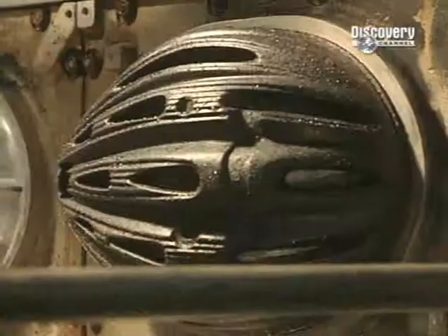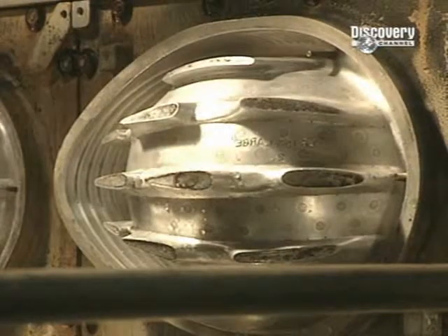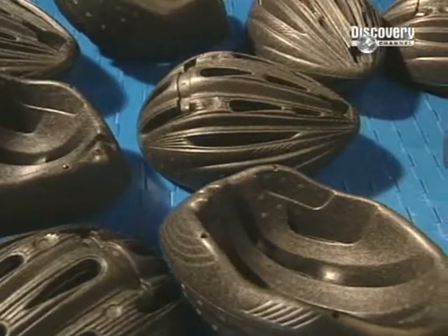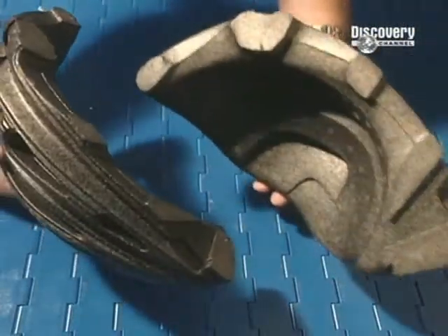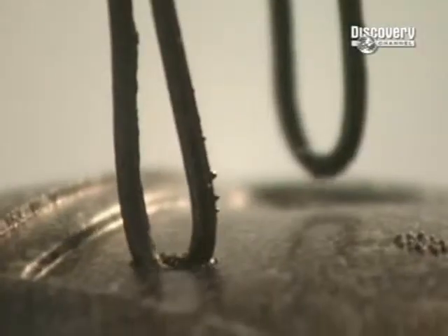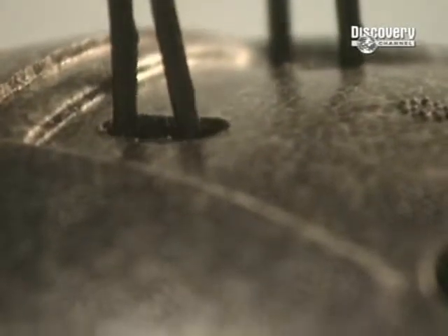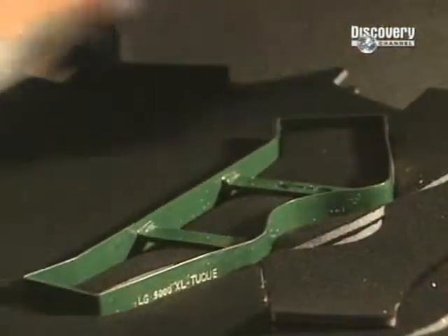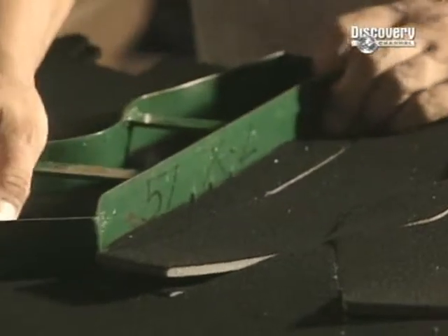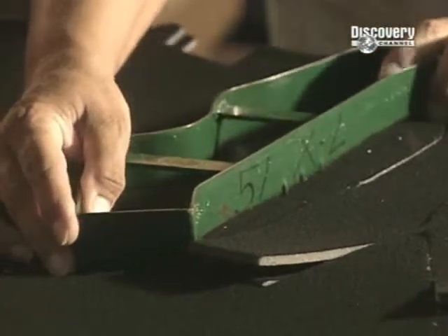The press closes up for 6 minutes. The particles are steam fused before being cooled with water. The foam is removed from the mould. Different designs are produced for different helmets. Depending on the helmet model, openings have to be made with this heat iron to allow for installation of an air vent. All that remains is to make the adjustment pads, cut with this press-powered stamper.